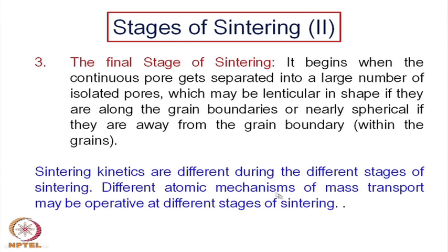However, the final conclusion is like this: the sintering kinetics are different during the different stages of sintering. Different atomic mechanisms of mass transport may be operative at different stages of sintering. So, it is not necessarily that the same mass transport mechanism will be operative, and their kinetics may also be different.